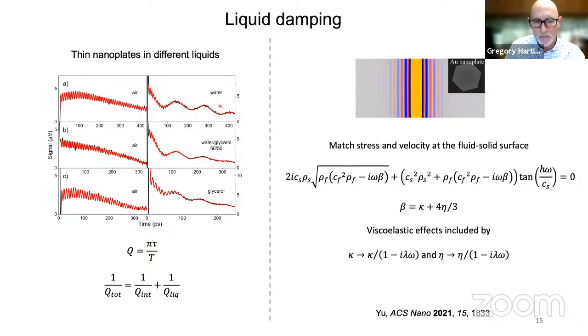Then he added different liquids, different water glycerol mixtures, and looked at the damping and worked out a quality factor for liquid damping. And then we compare that to this calculation to see if we can see viscoelastic effects.